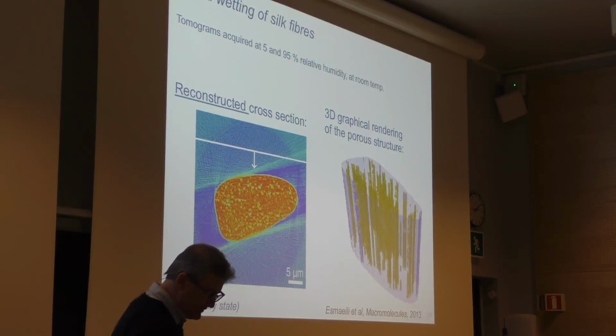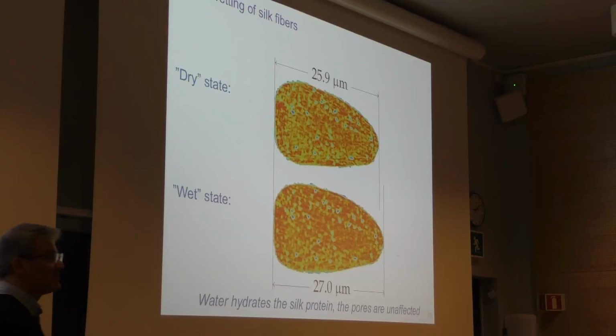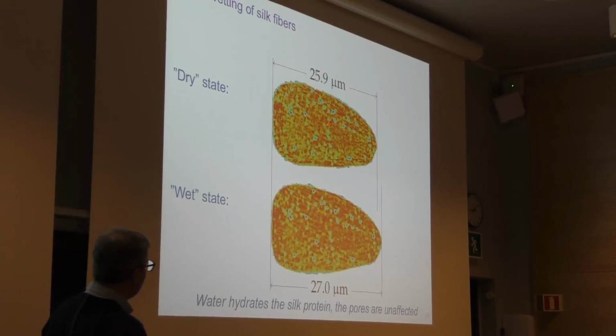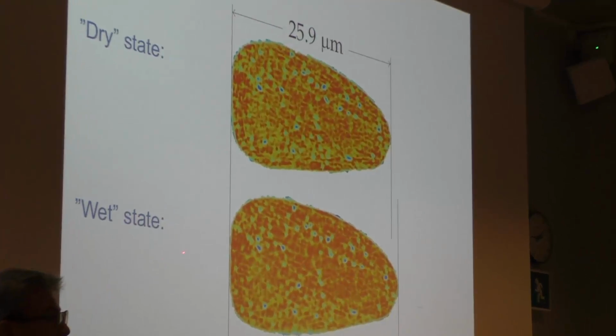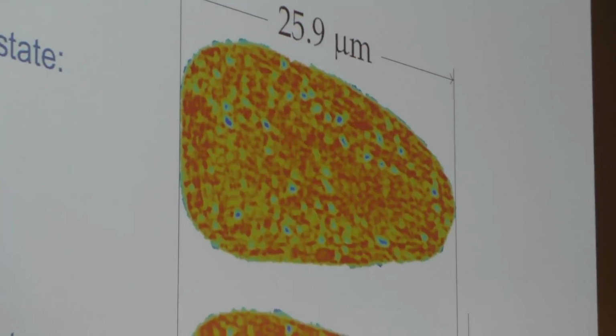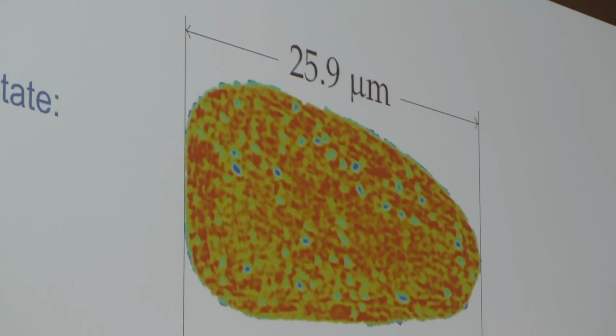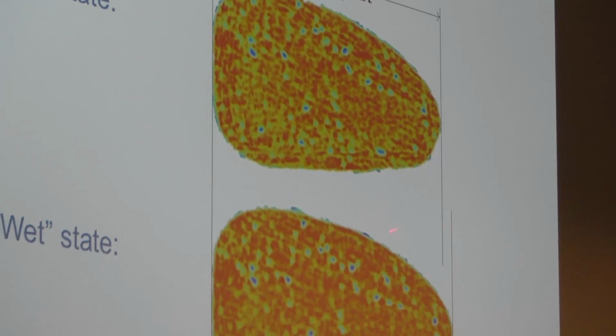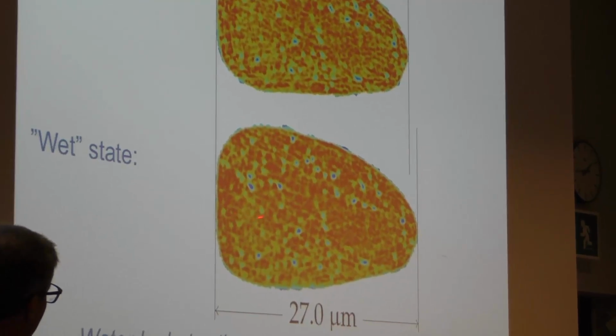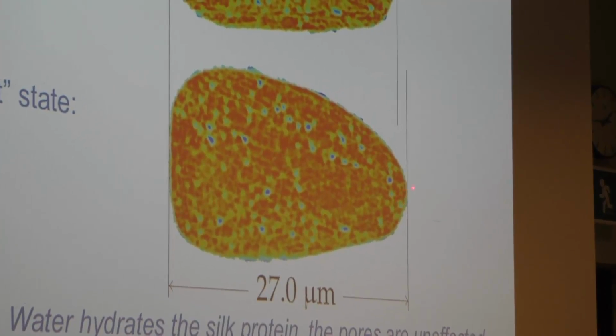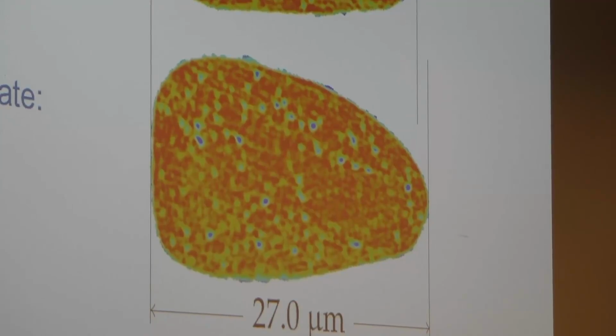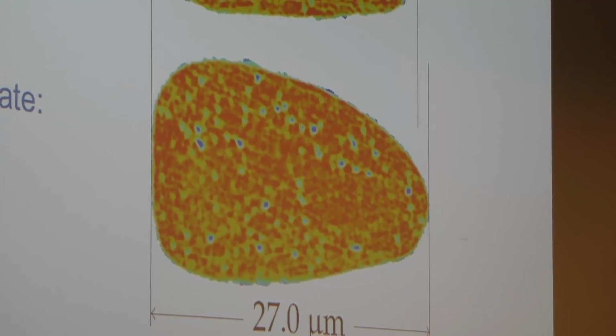So we measured this first in a dry state at the relative humidity of less than 5%. And then we measured it again in the wet state, meaning that the relative humidity was close to 100%. And indeed you can see that the silk fiber has expanded like you would expect.